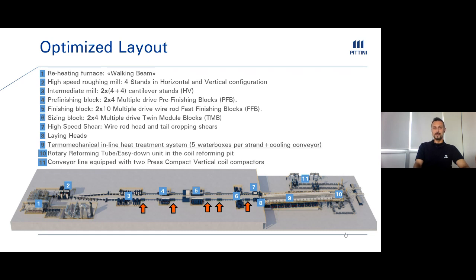Okay, but let's get back to the layout. After the high-speed roughing mill, we can see that the rolling mill splits into two different strands. Why is that? Because in this way, the rolling mill is able to guarantee the desired productivity, avoiding any issues related with the loss of quality of the product that can be linked to different rolling stocks. This is mainly related to the fact that we don't need to change the rolling speed during production.